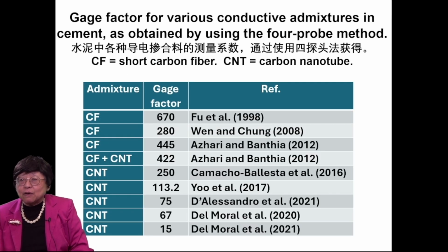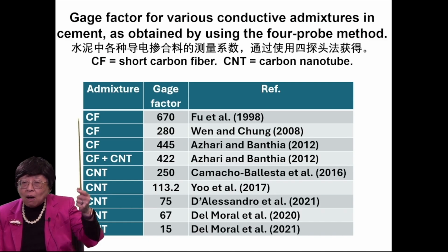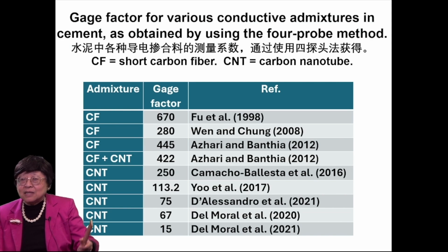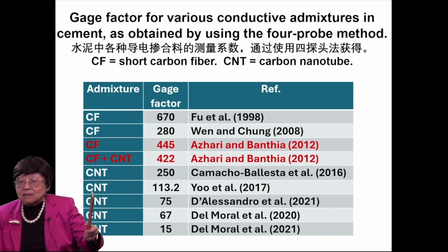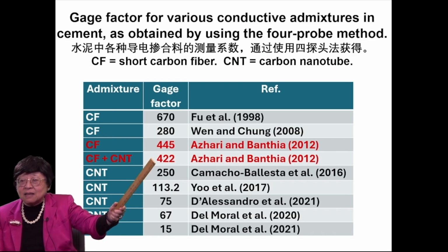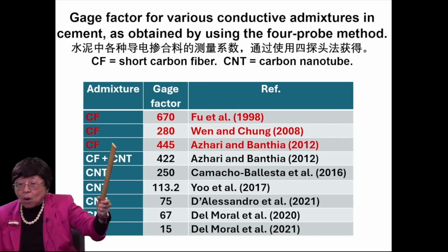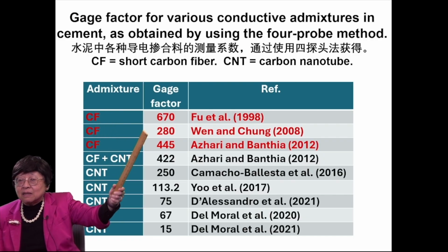This is the gauge factor for various conductive admixtures in cement as obtained by using the 4-probe method. I exclude the published results using the 2-probe method, so all these are based on the 4-probe method. CF means the short carbon fiber, and CNT is the carbon nanotube. And one sees that comparing CF versus CF plus CNT, with the CNT added, the gauge factor actually decreased. See? On the other hand, if one has only the CF and no CNT, the gauge factors are